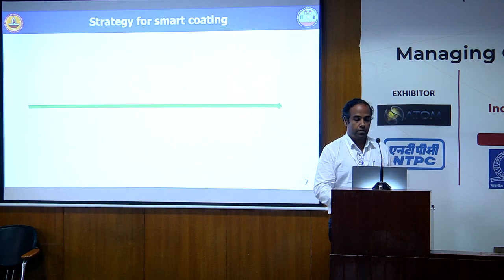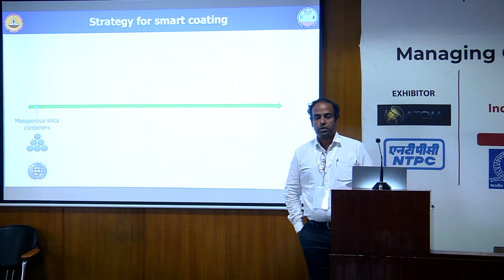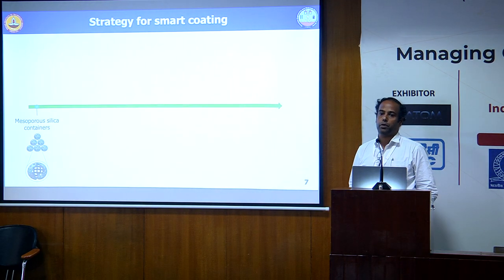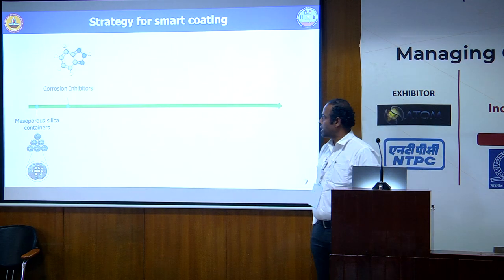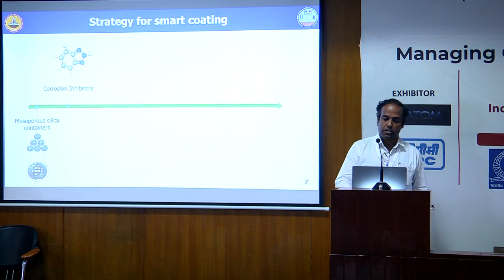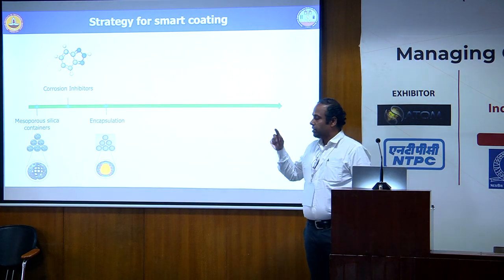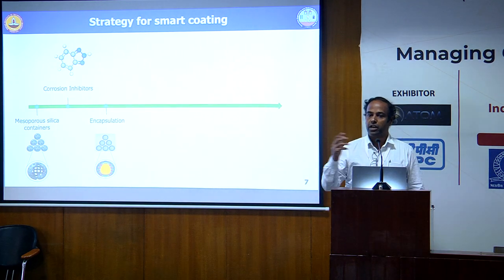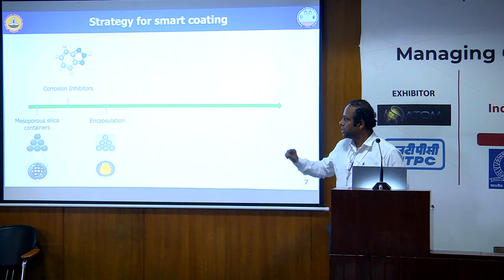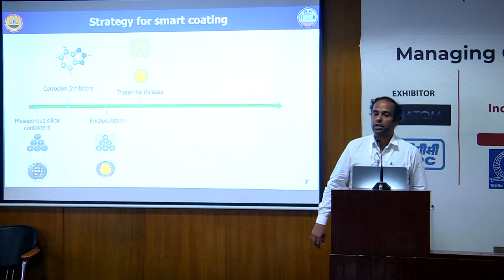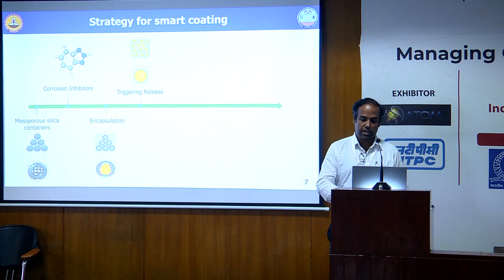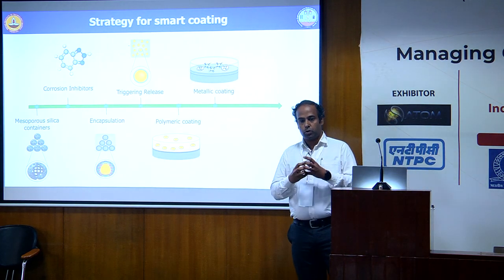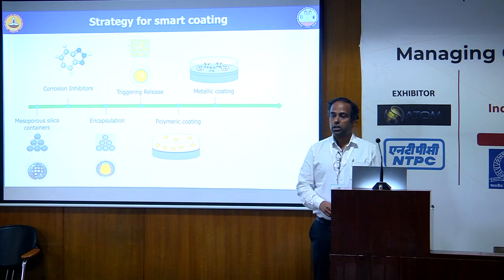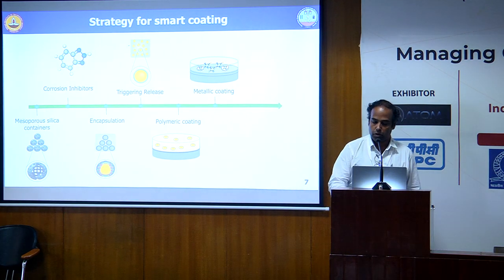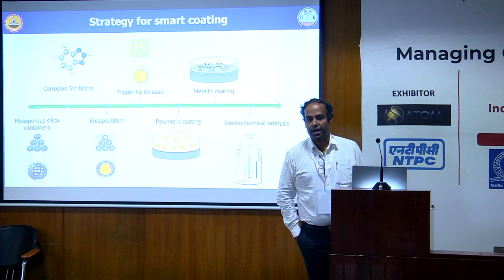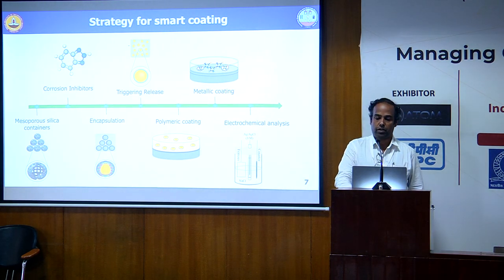So what is our strategy? We started with building containers. We found that silica, mesoporous silica, could be a possible container. Once we have mesoporous silica, we identified a set of inhibitors which can be put inside it. Then you cannot just put it inside a coating because it will release immediately. It has to release at the point of trigger. So we try to encapsulate it. Once you encapsulate it, when there is a local front where pH changes, it gets released. Then you can take this capsule and put it into a metallic coating if you want, or into a polymeric coating based on what you want to do. And finally, you can understand the corrosion behavior and how this performs. So this is our strategy for our smart coating.